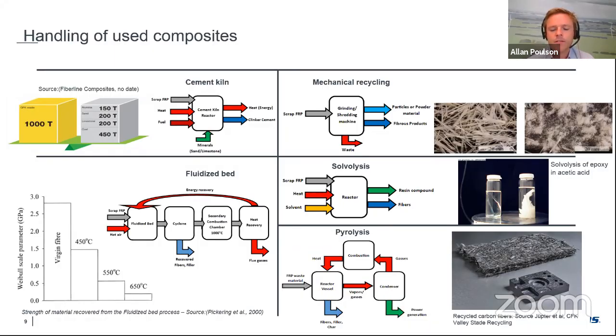The thing here is that the fibers lose some of their strength when they are solvolyzed or pyrolyzed or go into a fluidized bed. And also we're not talking about continuous fiber anymore. They're chopped into pieces, which means that we cannot use them in a wind turbine anymore. The thing is also that when it loses strength, let's play with the idea that you could actually make continuous fibers, and you could actually resize the fibers, the glass fibers.